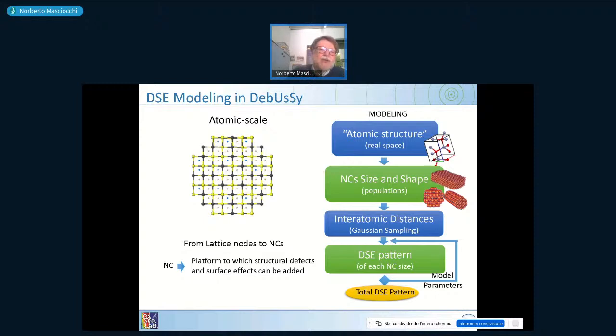Of course, by doing this, you can also introduce defects. You can just cut slices away, you can just substitute atoms. It's just up to you to define what your model is. So you go from lattice nodes to nanocrystals. This is the atomic structure. The atomic structure is something which may be known from a single crystal study or powder diffraction study from others. You introduce the nanocrystal size and shape not only as a circle, but for example as a sequence of spheres of different size. So you have size and shape in population.